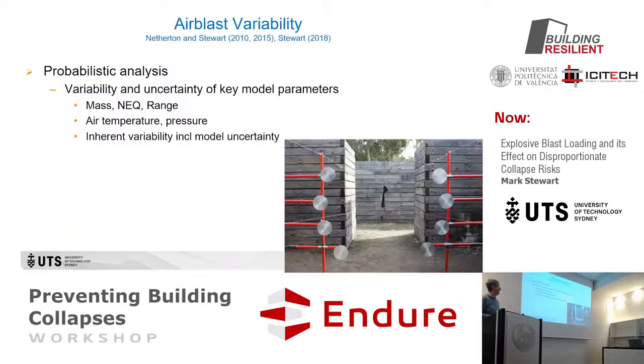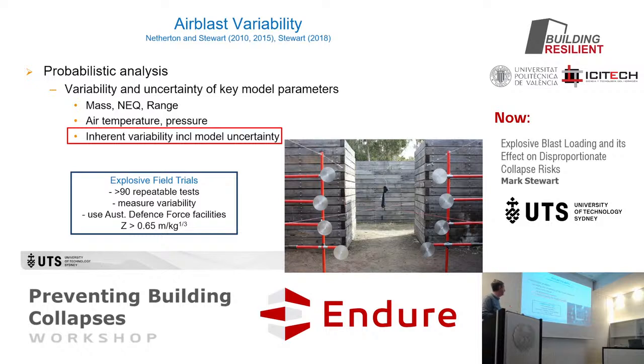So in terms of air blast variability, what we've done, in conjunction with the Royal Australian Air Force and the Australian Defence Force, is a lot of blast testing, maybe 1 to 2 kilograms. We have an explosive here and 8 pressure gauges, exactly the same. And we're trying to measure what variability we see at each of those gauges. Now, theoretically, you should get exactly the same pressure at every gauge. But we don't, right? We see that there's some variability. And so we did more than 90 tests over several years.